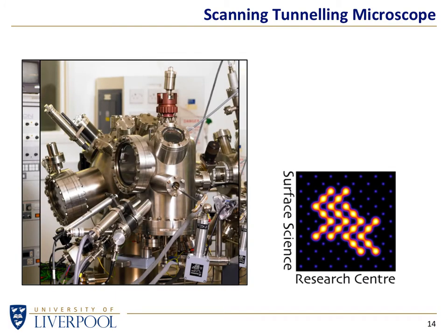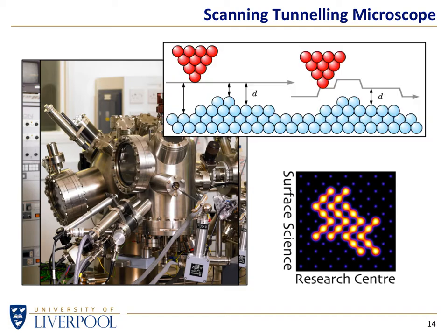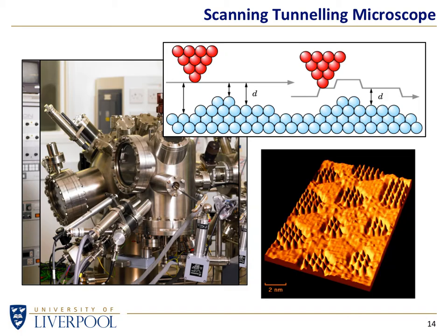This particular microscope is a scanning tunneling microscope. It's not one that's necessarily used for earth materials very often, but it does have very high resolution. It involves moving a very sharp tip over a surface. It's only a tiny distance, nanometers or so, just a thousandth of a micron, a millionth of a millimeter if you prefer, a billionth of a meter if you prefer, only a nanometer or so above the surface, and through a quantum mechanical process I'm not going to go into, it allows us to get individual resolution of atoms on a surface.